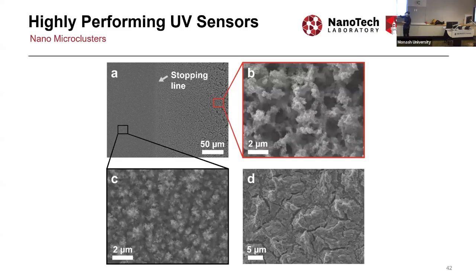If I recall it, or it's something that I would consider as not working because this is kind of damaged, and then in some cases it was washed away. But this one is a very small droplet, so you can see this section didn't change because the droplet was not enough to actually cover the whole area. But that section changed a little bit, but even that change is kind of different in terms of structure compared to the clusters. Thank you, Noushin.